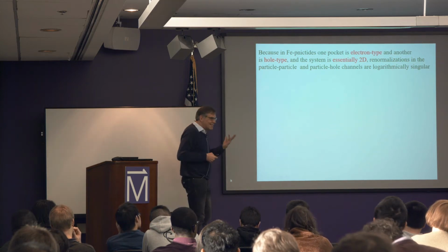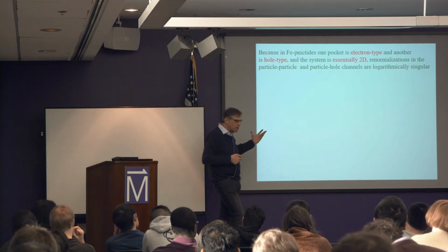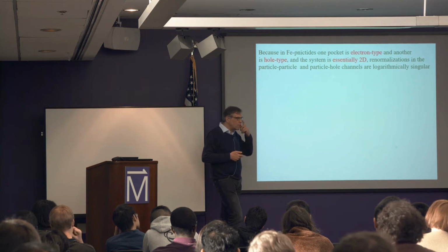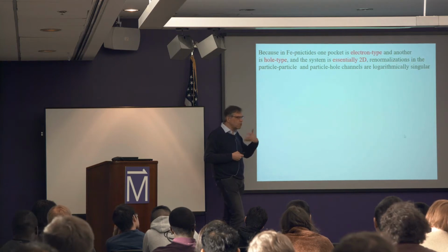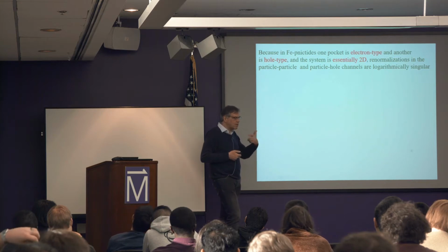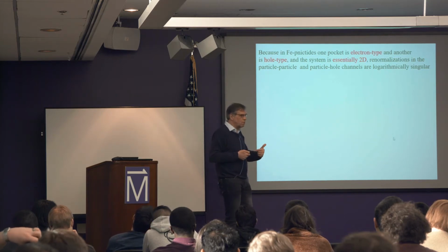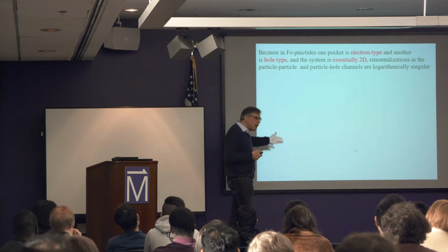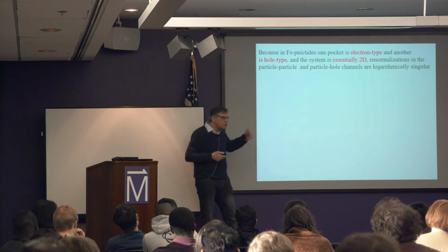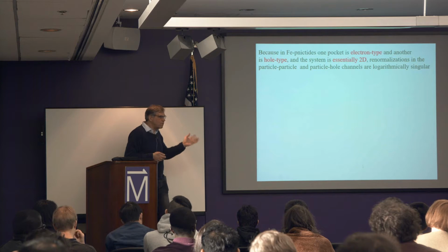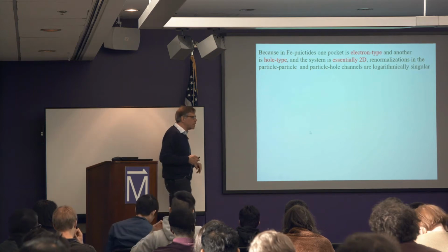Yes, the story with nematic order in iron-based materials. There is one approach to nematic order which tells you that nematic order is a precursor to spin density wave. Then the nematic order parameter by itself will be constructed out of four fermions, not two fermions. Then you can use these couplings and construct an order parameter which is a four-fermion object. This is a separate line of research. Okay.